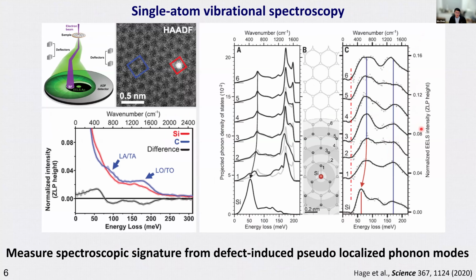And the results are actually based on one of the very important works 5 years ago published by the SuperSTEM group. What they demonstrate here is that using vibrational EELS or phonon EELS, they can actually sense the difference in the local vibrational signals introduced by a defect. In this case, it's a silicon defect embedded in the monolayer graphene lattice. So they compare the spectrum acquired from the pristine lattice and acquired from this point defect. So they can see the very subtle difference.